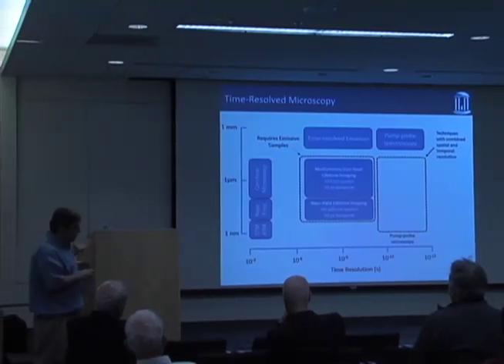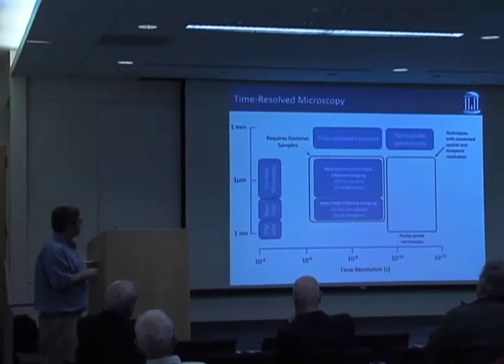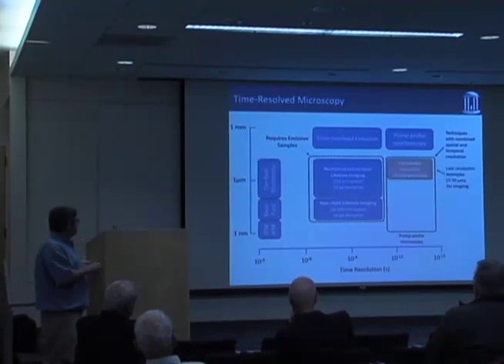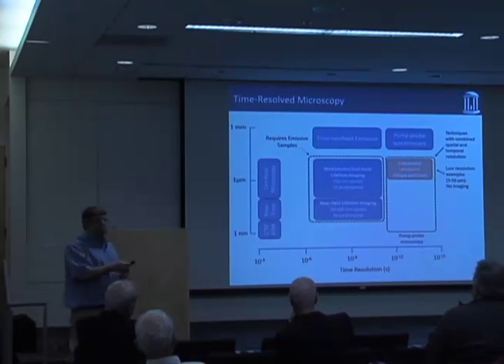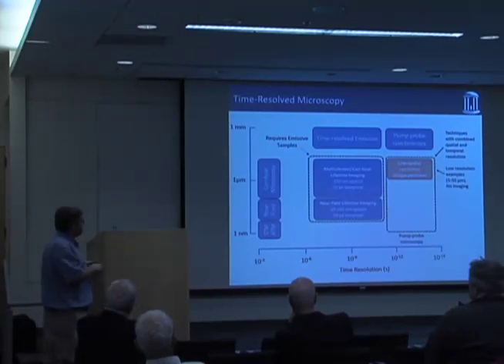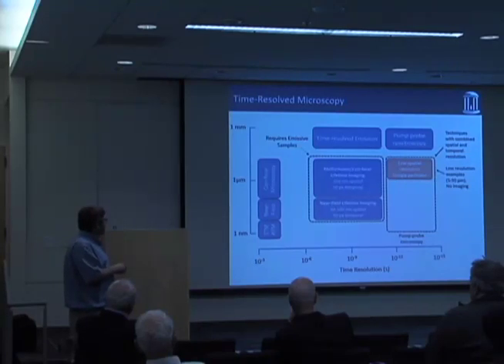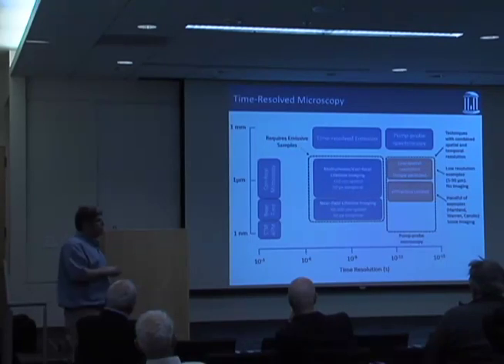There have been papers that have appeared over the last 15 or so years. In the beginning, they were all low spatial resolution. They take their laser pulse, focus it with a microscope objective down to maybe 5 microns or 50 microns, and look at single particles and that sort of thing. There was no imaging involved, although they were doing single particle type measurements. Later, my group and others started pushing that spatial resolution down to the diffraction limit, and that's where we're working. And there were several others doing this as well.